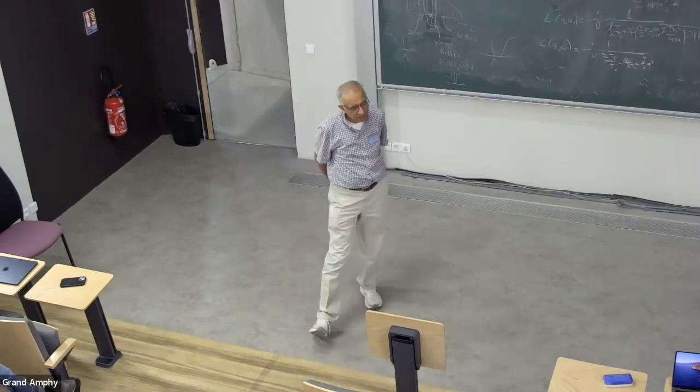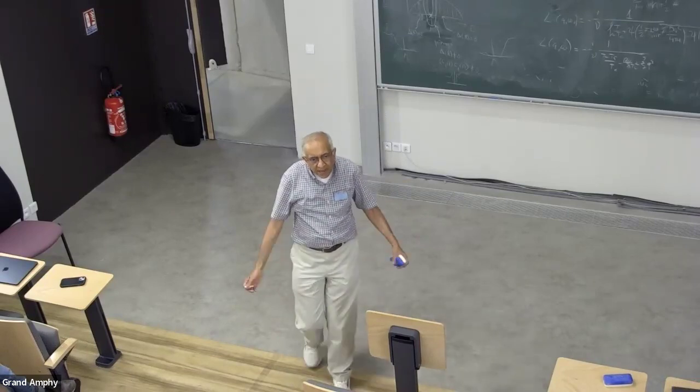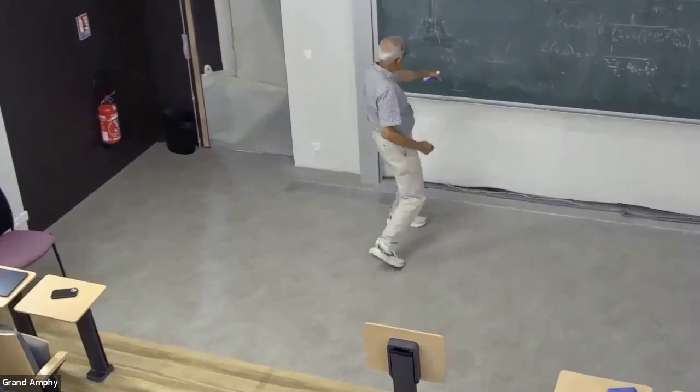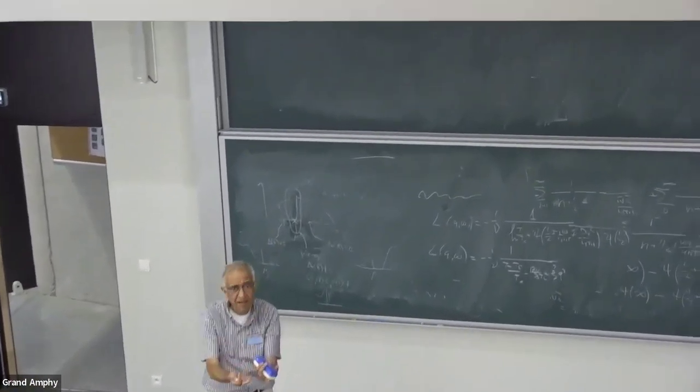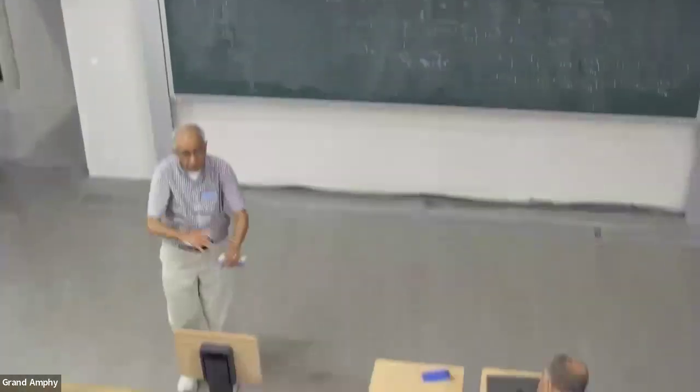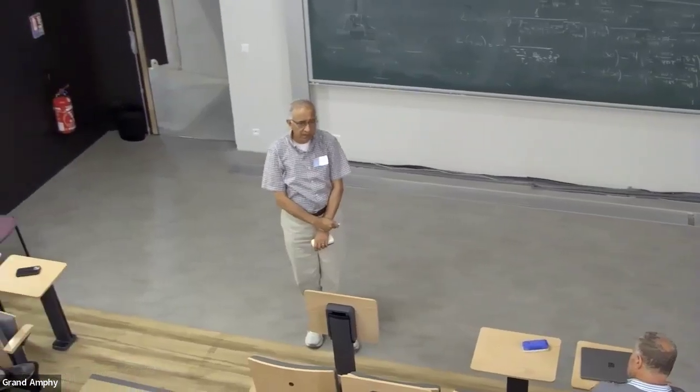Yeah, thank you very much. Okay, sure. So that's the intuitive picture. This idea that somehow the pairing amplitude and the energy gap are closely tied, as they are in homogeneous superconductivity, breaks down in a very dramatic way.